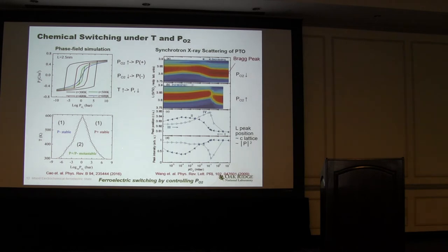Our work actually agreed with a recent experimental report using synchrotron X-ray scattering. We here show the Bragg peak, where the position of the Bragg peak is related to the lattice parameter of the C-axis, and it's also related to the magnitude of the polarization. We find that depending on whether the oxygen partial pressure is decreasing from a higher value or increasing from a lower value, the position and the intensity of the Bragg peak is dependent on